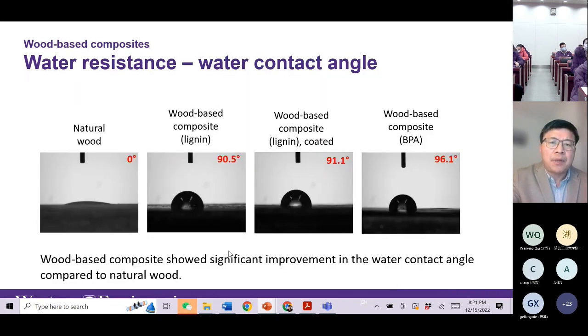Another property is the water contact angle. This water contact angle is used to check the surface morphology, the hydrophobicity. We can increase the water contact angle from 0 degrees to almost 90 degrees. So this surface is almost hydrophobic compared to the original natural wood. We make this material hydrophobic. That's why this material has high resistance to water, as we showed before in the previous slide.